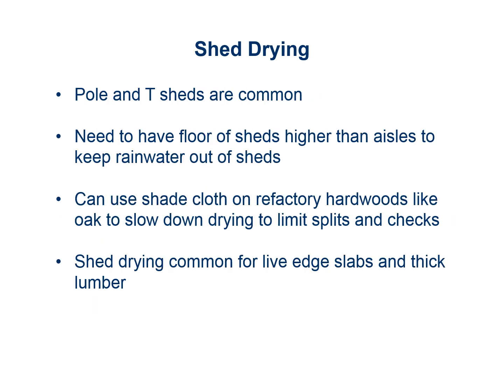Shed drying is a good way to air dry lumber outside. Pole sheds and T-sheds are very common. You need to have the floor of the shed higher than the aisles to keep the rainwater out. A lot of times over time you'll put down a lot of gravel in the aisleways, and the next thing you know your rain is going into the buildings and you got to stop and do some grading. So you have to pay attention to that. You also want to watch gutters and the flow of water in the yard. You can use shade cloth on the refractory hardwoods like oak to slow them down and limit splits and checks.